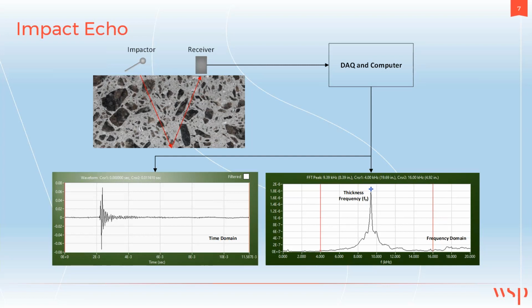That stress wave is referred to as a P wave, a compression wave, and will travel into the element and then reflect from boundaries back to a transducer or receiver that's placed near the point of impact on the surface. That transducer will translate the mechanical motion into an electrical signal that's collected by a data acquisition system and recorded in what we call the time domain.